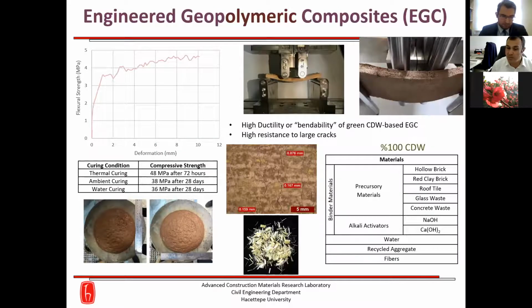So we also included fiber materials in the construction demolition waste-based geopolymer concretes to obtain high ductility or bendability of green CDW-based engineered geopolymer composites, shortly EGC. And in this way, we obtained engineered cementitious composites which have high resistance to large cracks, resulting in multiple narrow-spaced crack formation, as you can see in the figures or photos in the middle of the presentation. We obtained our best results among 100% construction demolition waste-based engineered cementitious composites as more than 45 megapascal after 72 hours thermal curing.